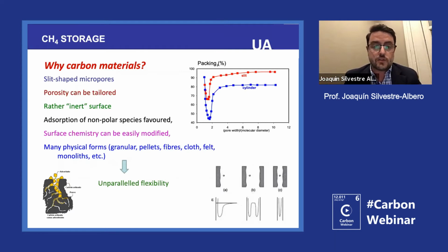Of course, there are also other advantages, like in the case of the carbon, you have slit-shaped micropores. So you have a higher packing density compared to cylindrical or spherical pores. The surface of the carbon is rather inert, so that means that you can get rid of the methane, or you can do the desorption quite easily, and that means a high working capacity. We can also play with the physical form. So at the end, you have a large versatility that makes the design of carbon materials very attractive for this specific application.